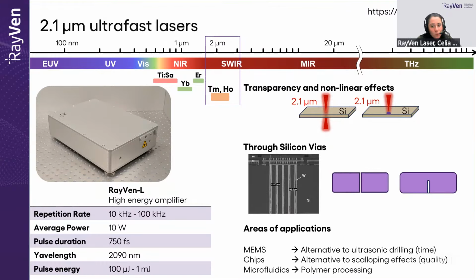We have currently two products. The first one, I haven't put it here because I don't think it's relevant for laser drilling, is an oscillator, RayVen S, that is emitting 1 watt at 2.1 micrometer of central wavelength, 100 femtoseconds, 10 nanojoule, 70 megahertz. And RayVen L, which can still be tuned, between 10 to 100 kilohertz, so between 100 microjoule and 1 millijoule, you make the calculation, 10 watts of average power.